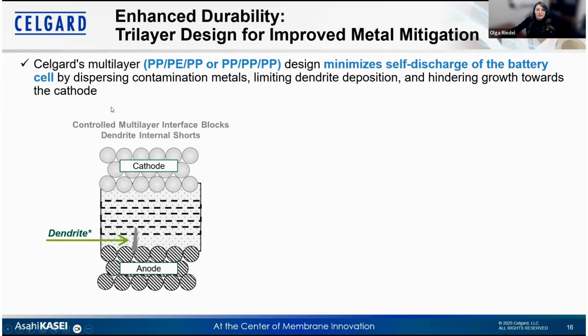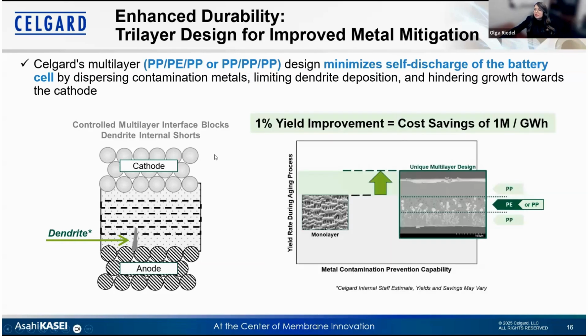Trilayer separators provide, however, additional benefits besides safety, also by mitigating metal contamination. Their layered pore structure also improves the electrolyte distribution and helps maintain a uniform ion flow, which minimizes, on the other hand, localized current densities. This reduces the risk of lithium plating, dendrite formation, and microshorts that can normally cause self-discharge, ultimately enhancing both cycle life and also safety. We estimate that utilizing Trilayers in newer cell design can actually improve manufacturing yield by about 1%, which represents roughly $1 million in cost savings per gigawatt hour of production.